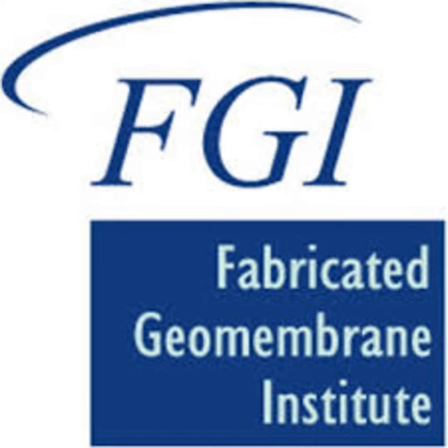The three main concerns would be polymeric degradation, which we kind of talked about a little bit before. That could lead to a potential strength loss. And we have clay compatibility, which more negatively influences hydraulic connectivity, because we're going to influence that double layer of the clay versus, we increase the strength of the bentonite in that case. And then we have potential clay dissolution.